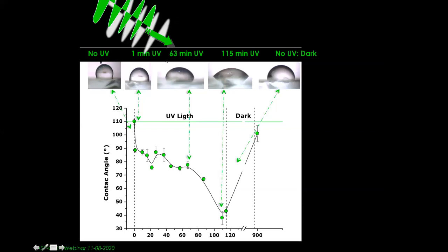But nonetheless, with the time from 1 minute to 63 minutes, you can see that the contact angle changes. It moves from this value here, over 90, to a smaller angle and so on. Remember the contact angle. The higher the amount of illumination, the smaller the contact angle. As you can see, it decreases.